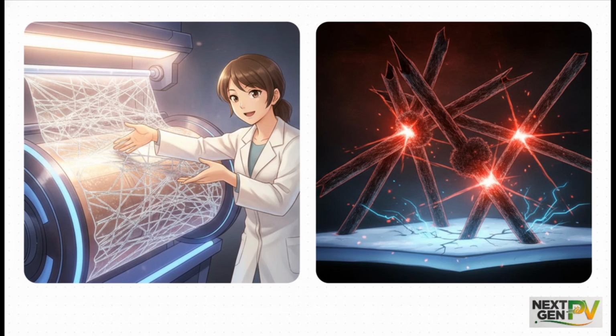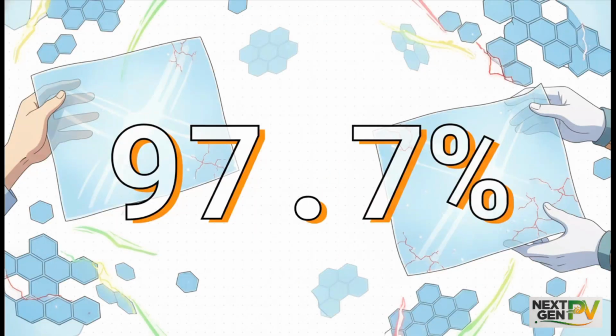Then there's graphene, a single atom-thick sheet of carbon. A single layer of graphene offers a staggering 97.7% optical transparency. That's wild. It's exceptionally flexible, chemically stable, and lightweight. However, right now, taking this miracle material from the lab to large-area commercial fabrication is just a massive challenge. Transferring large sheets of it often results in microscopic wrinkles and cracks, which creates high sheet resistance.